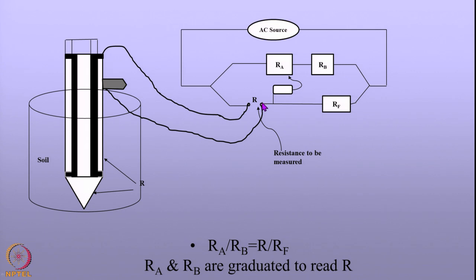The unknown resistance, or the resistance of the soil, is measured by balancing this resistance actually. Okay. You change this resistance value, there are two resistance values Ra and Rb which are known, fixed values, and Rf is a variable resistance, you start moving actually, and using this relationship Ra upon Rb equal to R upon Rf, it is possible to determine the R value. The advantage of this technique is it is very versatile, simple, it can be taken to the field.